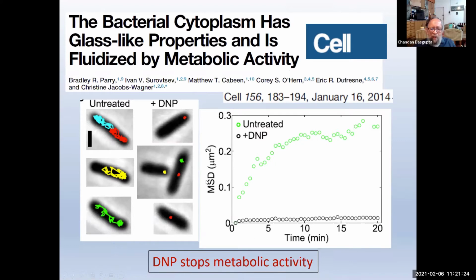And this is also seen in the mean square displacement as a function of time. When the tracer is moving around, the mean square displacement increases as a function of time, and eventually saturates because it's diffusing in a finite system. One can understand this dependence on time from diffusion. But when DNP is added, then it doesn't go anywhere. There's a very small value of the mean square displacement, which doesn't increase as a function of time. So this is similar to a glass transition, as one is turning off the metabolic activity. And that is what it says, that the activity basically fluidizes the system. When there is no activity, these particles will not diffuse, and the medium will behave like a glass.